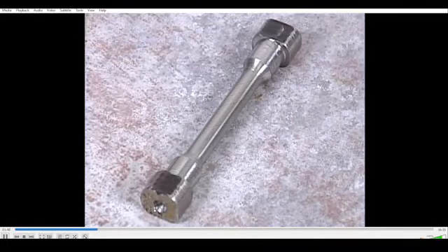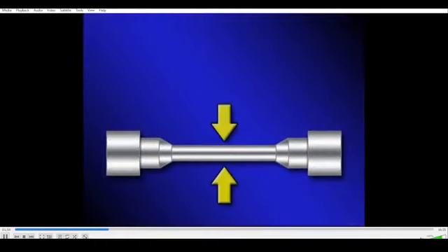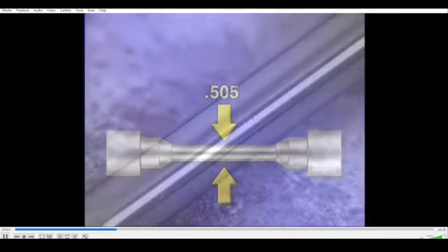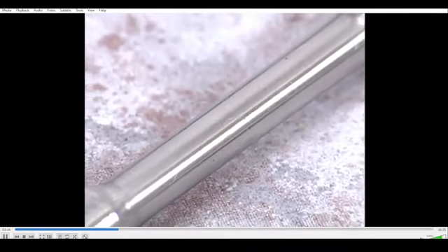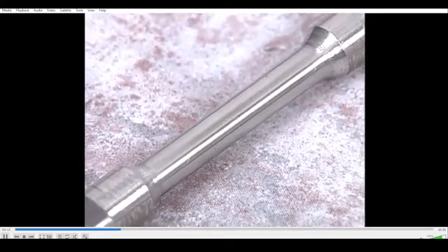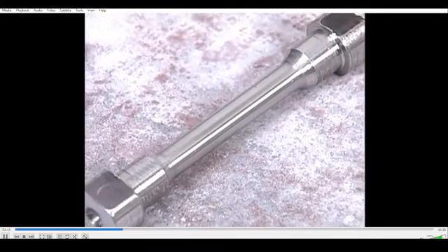The reduced section of the specimen is usually tapered about 5/1000 inch from the ends to the center. This allows the fracture to occur approximately in the center, where the specimen is thinnest. The diameter at the center will vary depending on material thickness and code requirements. They are sometimes used as names to describe the tensile. For example, an inspector may call for a 505. The finished surface should be smooth enough to prevent premature failure. A rough surface could cause a fracture in an undesirable location.